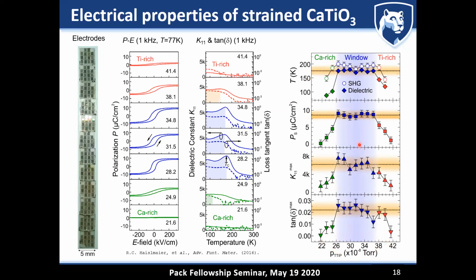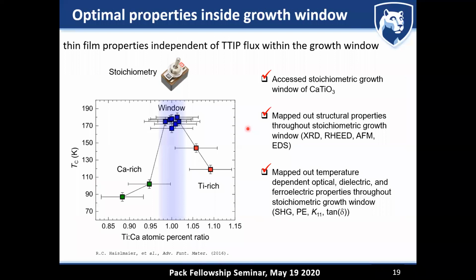And what you can see, again, is that all of the physical properties of the film nicely mapped onto the fact that we had a growth window. You can see that the dielectric and ferroelectric properties did not change throughout the self-regulated growth window, but as soon as you deviated from these self-regulated stoichiometric growth conditions, we saw a deterioration of the properties. So really, what I'm trying to get across here is that we're able to optimize properties if we are able to access a growth window. And this is also true for oxides.